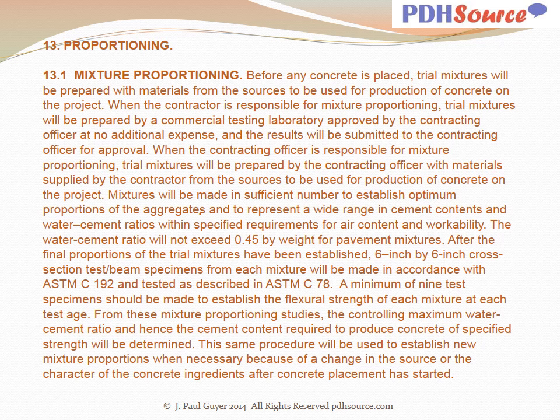When the contracting officer is responsible for mixture proportioning, trial mixtures will be prepared by the contracting officer with materials supplied by the contractor from the sources to be used for production of concrete on the project. Mixtures will be made in sufficient number to establish optimum proportions of the aggregates and to represent a wide range in cement contents and water-cement ratios within specified requirements for air content and workability. The water-cement ratio will not exceed 0.45 by weight for pavement mixtures.